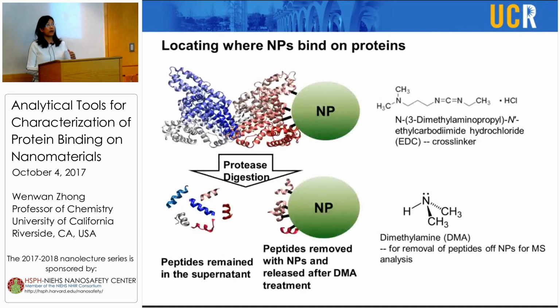So to confirm this, we also conducted mass spec analysis to find out which peptides are located at the interaction interface, trying to see why the functional group is so important. This iron oxide surface has a rich carboxyl group. So we do labeling, cross-linking between this carboxyl group and the amine group on a protein, and then we digest the protein, leaving only the peptides very close to the nanoparticle cross-linked onto the nanoparticle.